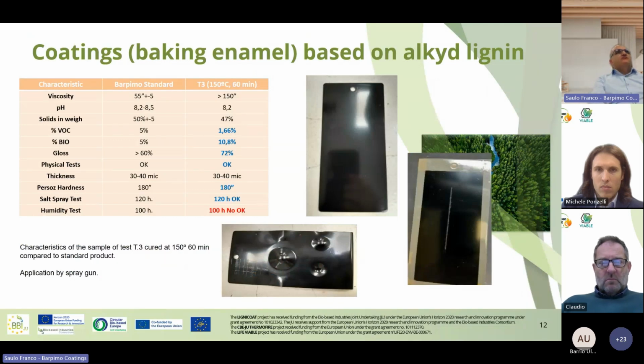In Barpimo, we formulate coatings for bake enamel, and here we have the standard characteristics for our standard paint, and then formulated with the new resin based on lignin. So the viscosity is a little bit higher with the lignin modification, and the pH is similar, solids are similar. VOC, of course, as we introduce new raw materials, we were able to achieve a very reduced VOC.